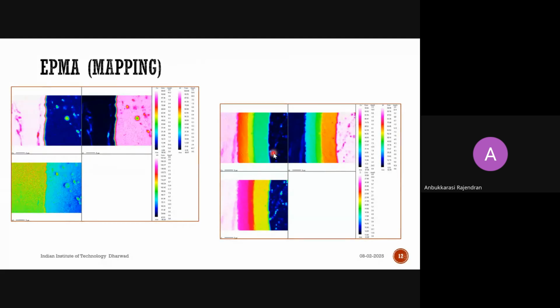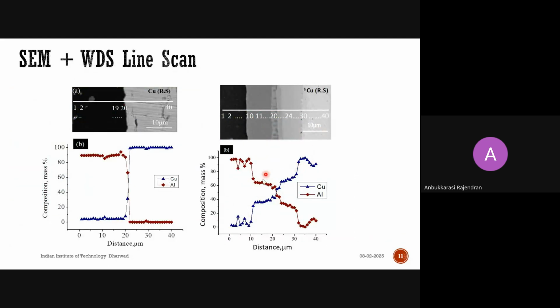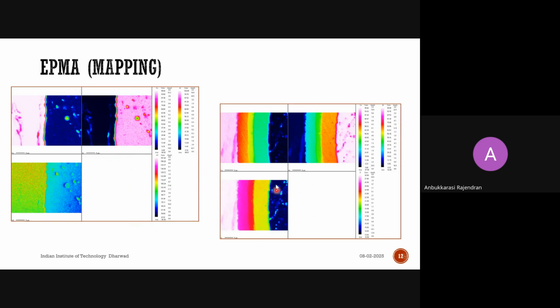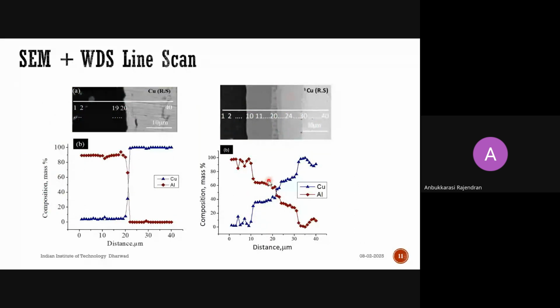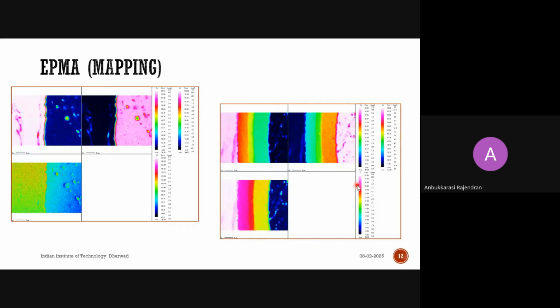The same region after heat treatment shows how much the diffusion has changed. So whatever variation I could see here, qualitatively, how the distribution is at the interface, I can see by doing the mapping. So this is a kind of qualitative analysis, while the other gives the quantitative value of the particular composition. So this mapping is qualitative compositional mapping, which shows qualitatively how that particular selected element is distributed within the selected region.